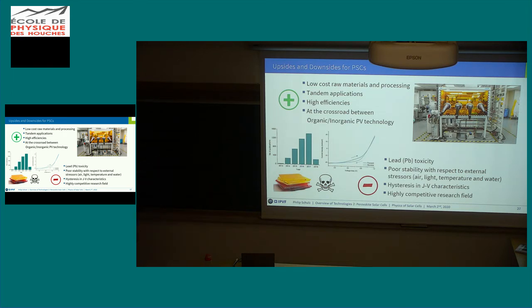And then also the hysteresis, I mentioned it only in passing, but this is a typical instance of hysteresis where you see a change of the JV curve depending on your scan direction and the history of the cell. So what does this mean? It means that there is some inherent metastability built in these devices that changes as you measure it. So this will change a lot for your equation once you make it into a device and want to calculate the exact power output. But more so, it also carries some implications on the final stability of such a compound.